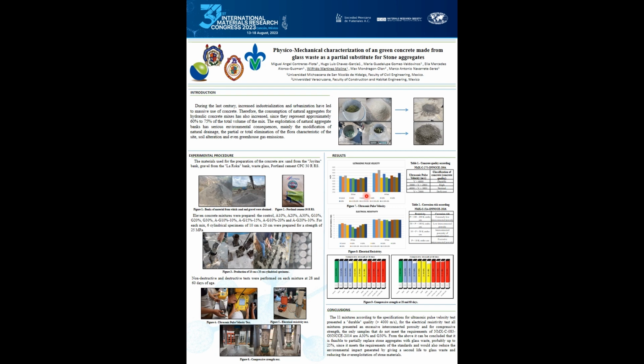The results for the ultrasonic pulse velocity test indicate that all the mixtures present results greater than 4,000 meters per second, presenting a durable quality. For the electrical resistivity test, all the mixtures are below the minimum specified limit, indicating excessive interconnected porosity. And for the compressive strength test, we can observe that the only ones that do not meet the designed strength of 25 megapascals are the A30% and G30% mixes.